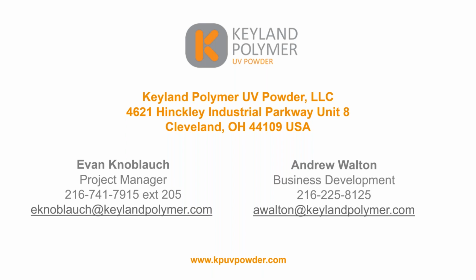If the question is about applying additional coats on top of UV powders, we have a lot of experience on that, specifically on MDF wood, where we're using the UV powder as almost a sealer. On a wood substrate that's porous, it's going to almost encapsulate that part, so that instead of having to put 5 coats of wet paint on it, you can just do a top coat and a seal or something like that. So we do have some experience with using a UV powder as a primer type of coat with additional liquid top coats on top of it.